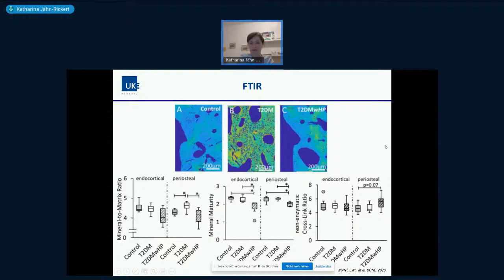And what is really interesting, and one of the bone quality factors that could become more and more important, are these non-enzymatic crosslinks that one can determine also with FTIR as a crosslink ratio. She found that these were at least slightly upregulated with the high porosity, indicating that the collagen becomes stiffer due to these crosslinks, and therefore could change its behavior, potentially affecting fracture risk. And this is really exciting.